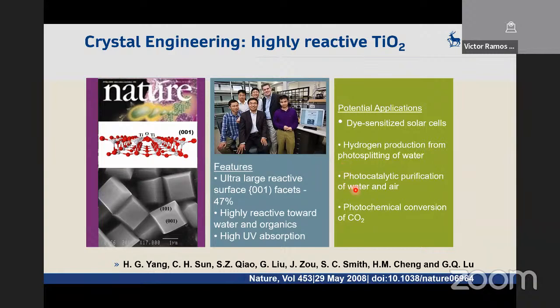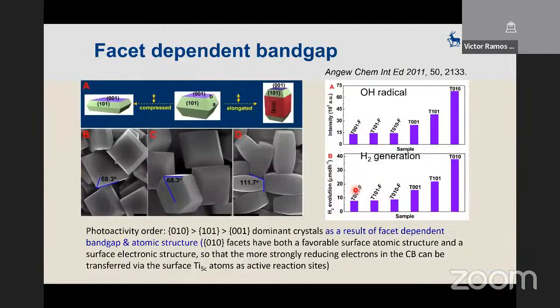We were the first to realize this in the lab by growing these crystals, and we can actually tailor the crystals to have lower index and more of this flat surface, which is the 001 phase. And then this elongated phase, which is here, that's the top. You can also produce this kind of elongated crystals that has a 010 phase.